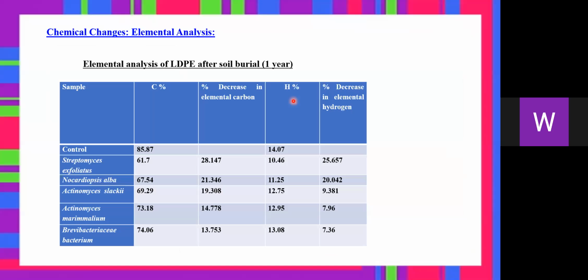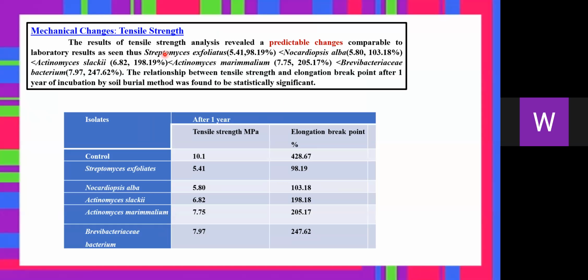Elemental analysis of LDPE after 1 year. Here too, compared to the control, Streptomyces exfoliatus exhibits a major decrease in elemental carbon, followed by other organisms in decreasing order. Tensile strength. The result of tensile strength analysis revealed predictable changes comparable to laboratory results. As seen, Streptomyces exfoliatus 5.41 is given in decreasing order, followed by Nocardiopsis alba, Actinomyces slackii, Actinomyces marimmalium, and Brevibacteriaceae bacterium. The relationship between tensile strength and elongation breakpoint after 1 year by the soil burial method was found to be statistically significant.